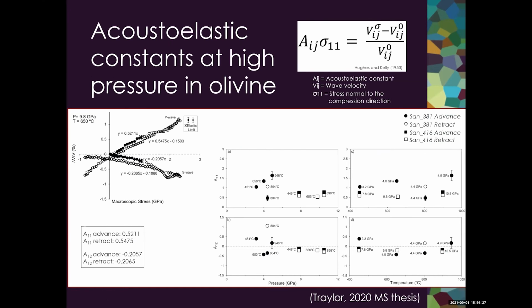So by using EPSC modeling to derive the bulk stress via the diffraction data, we can then plot the wave velocities in our experiment as a function of the stress state to obtain these acoustoelastic constants. This figure on the left shows the percentage of wave velocity change as a function of the macroscopic stress for an experiment performed at 9.8 GPa and 650 degrees Celsius, where we took measurements during differential ram advancement and during a differential ram retraction, maintaining the same strain rate.